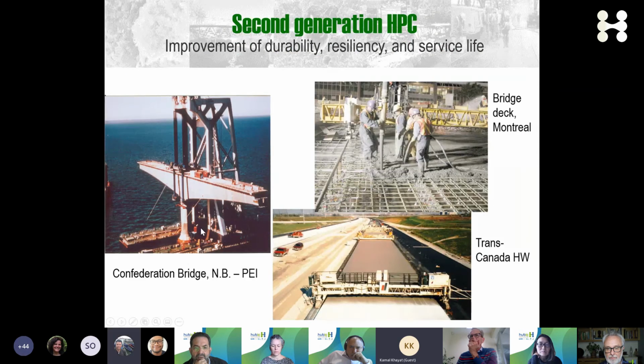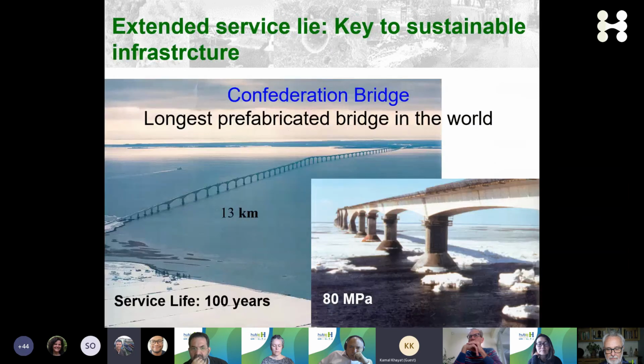Second generation is high performance concrete, which is really the one that is very used, and that is seeking high service life, seeking durability in marine structures, in bridge decks in urban areas, as well as in pavements, where you can get 50-year plus service life. But in bridges, especially, they are subjected to very high solicitation, in this case a marine environment. This bridge here is the longest bridge at the time it was constructed. It was inaugurated in 1997 in Eastern Canada, and the service life that was designed for that bridge was 100 years.